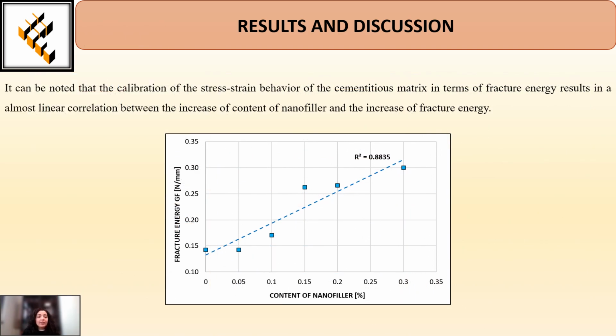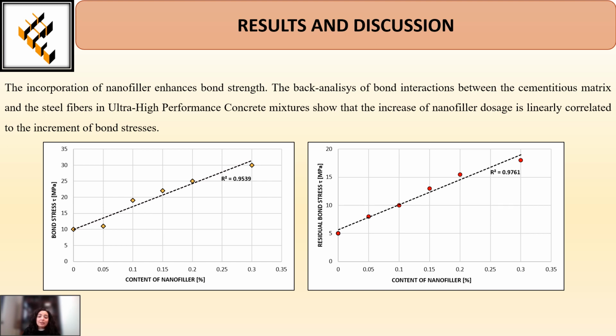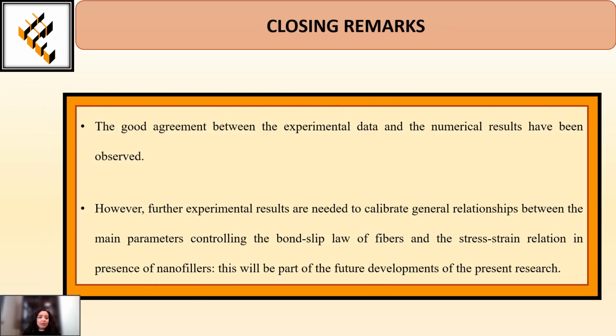Then it can be noted that the calibration of the stress-strain behavior in terms of fracture energy results in an almost linear correlation with the increase of nanofiller content. At the same time, the back analysis of the bond interaction between the cementitious matrix and the steel fiber shows that the increase of nanofiller dosage is linearly correlated to the increment of bond stresses. In the end, a good agreement between the experimental data and the numerical results has been observed.